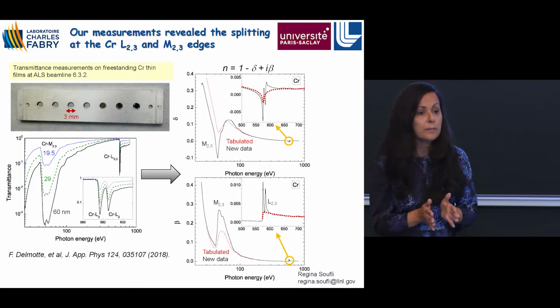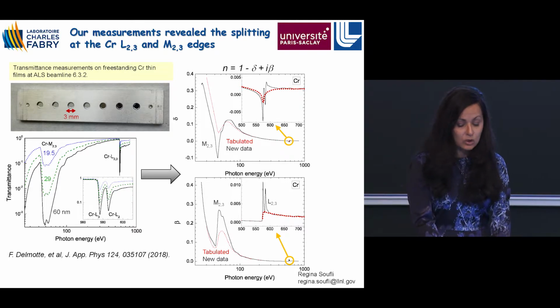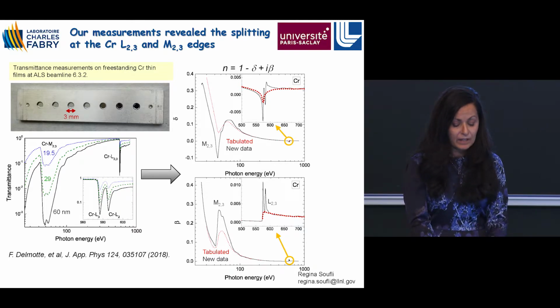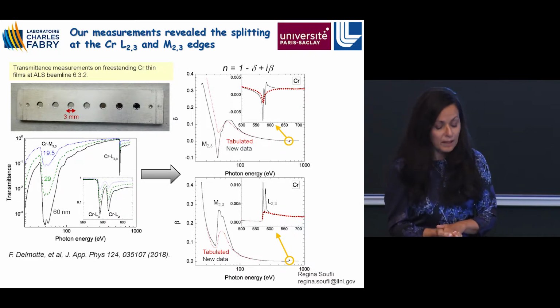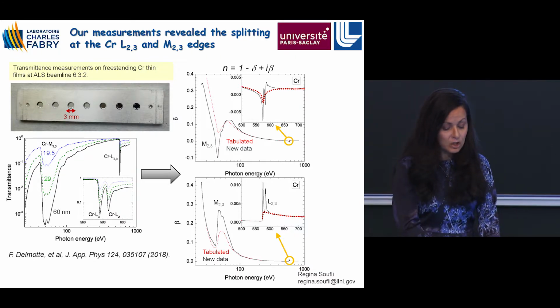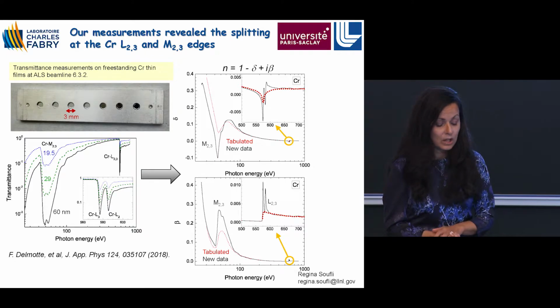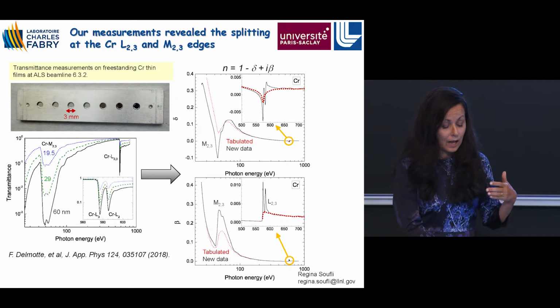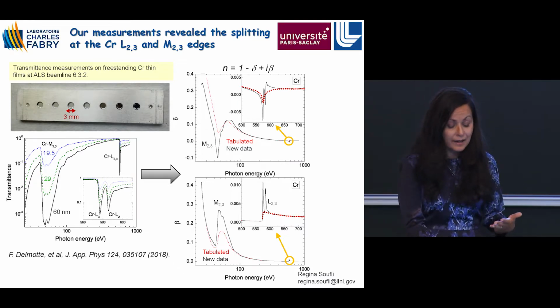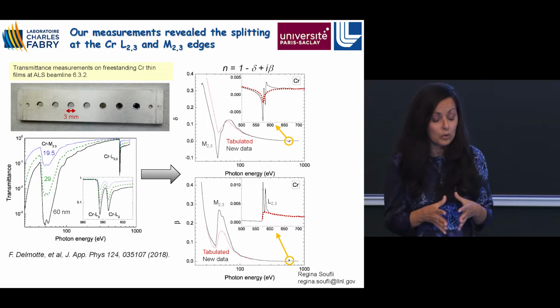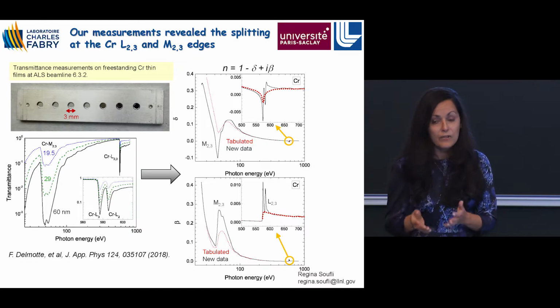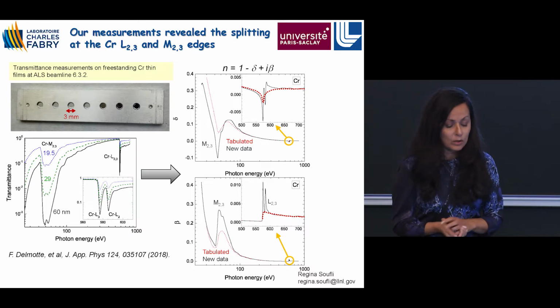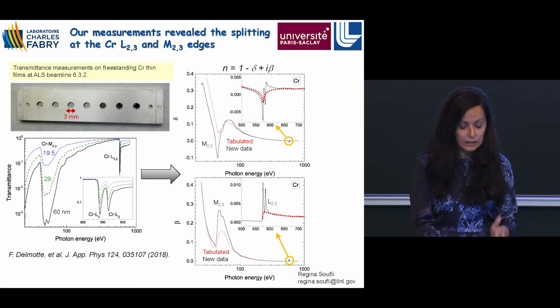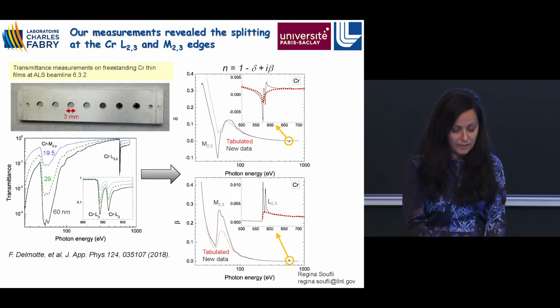And then you have to deal with imperfections of the light source. In this case, we determined that the light source has 1%, just 1% of spectral contamination that happens to be in this region of the chromium L23 edge, where the absorption due to the monochromatic beam is higher than the absorption due to the spectral contamination. And there is no straightforward way to remove that contamination. So Frank came up with a very clever model, and he was able to remove that contamination effect, which presented the problem in the analysis of the data. And so finally, we were able to analyze this data.